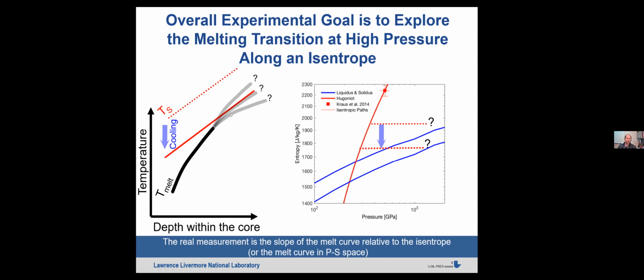Or one can even imagine a melting curve that is shallower than the slope of the isentrope, which would mean you would get solidification at greater or lower depths, say at the core mantle boundary first, and then that would snow iron down into the center of the core, which may inhibit convection or may just weaken the magnetosphere. So again, what we're really looking at is the slope of the isentrope relative to the melting curve.